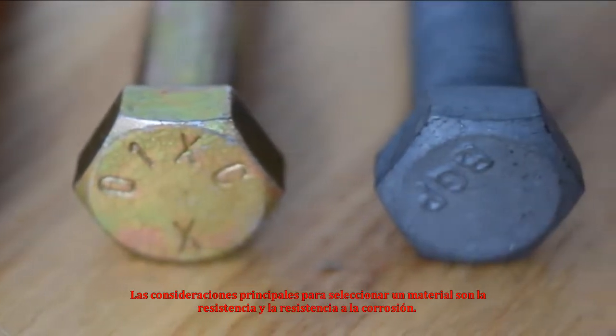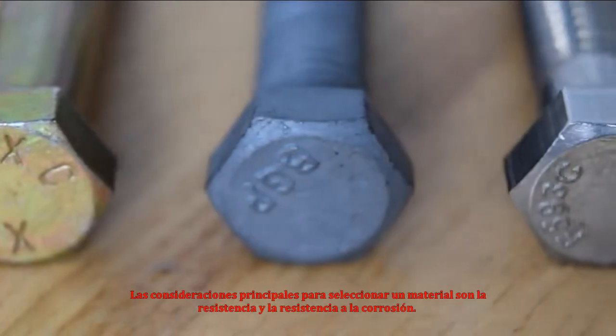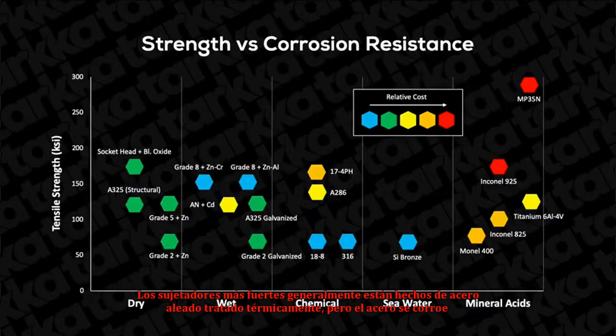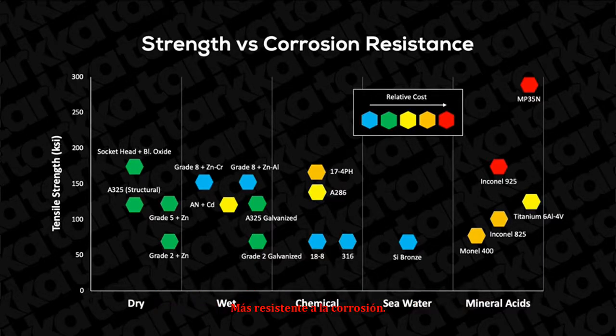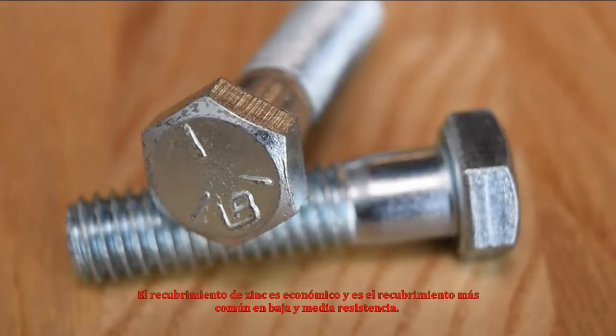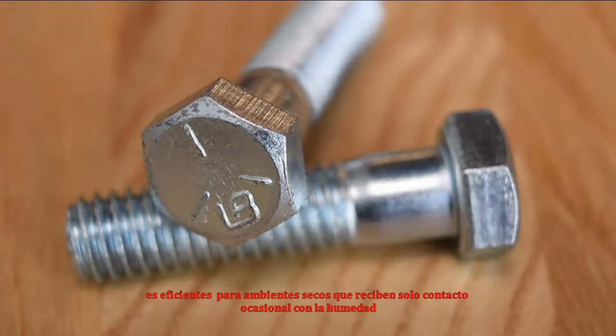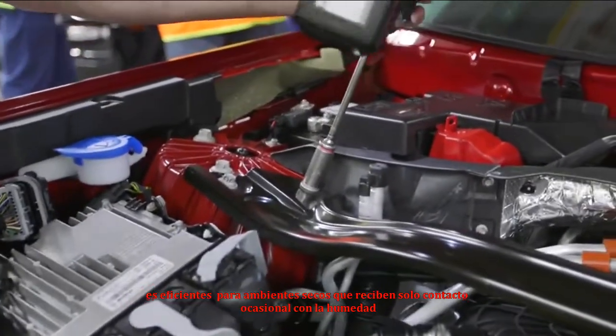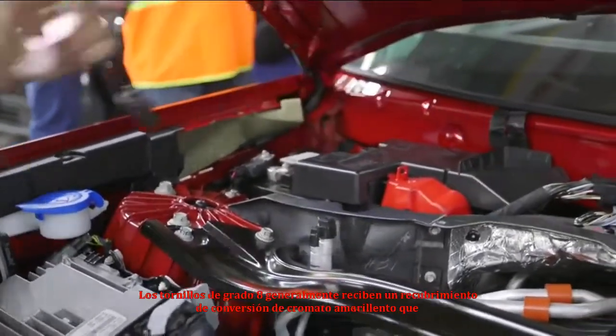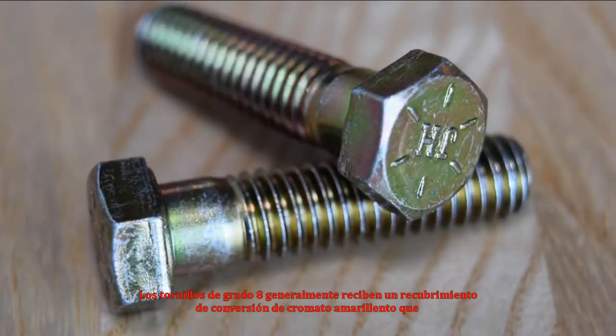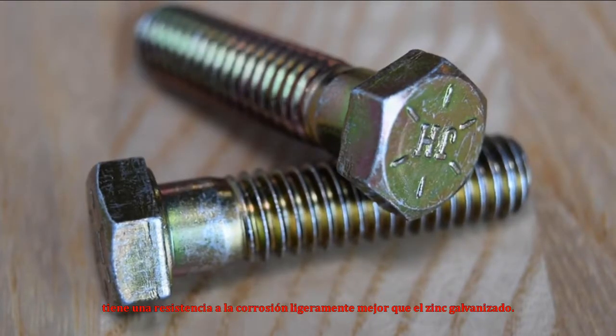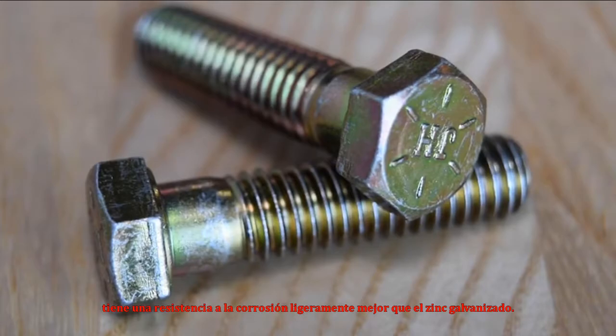The primary considerations for selecting material is strength and corrosion resistance. The strongest fasteners are usually made from heat-treated alloy steel, but steel will corrode when exposed to moisture. Coatings are commonly applied to alloy steel fasteners to make them more resistant to corrosion. Zinc plating is economical and is the most common coating on low and medium strength fasteners. It is sufficient for dry environments that receive only occasional contact with moisture. Grade 8 screws usually receive a yellowish chromate conversion coating, which has slightly better corrosion resistance than electroplated zinc.